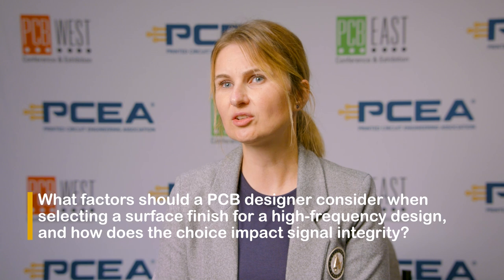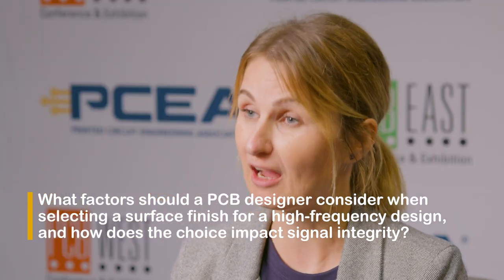A PCB designer should take into account the following factors when considering the substrate for high frequency applications. Surface roughness, that's for sure. The dielectric constant. Then conductivity and resistivity of the surfaces, corrosion resistance, oxidation resistance, and then the thermal stability. And this is important because, for instance, if I'm going to choose a surface finish in the form of hot air solder leveling, then I need to be aware that this kind of surface finish is going to create a very high roughness on the surface. And high roughness means that we are going to degrade the signal integrity. So in order to avoid this mistake, we might move towards a surface finish related to immersion gold, which normally provides a very smooth and very well conductive surface. So that also minimizes the losses of the signal integrity.